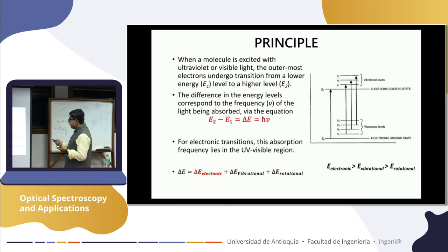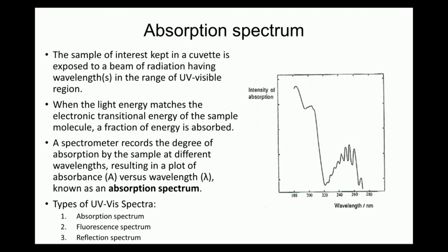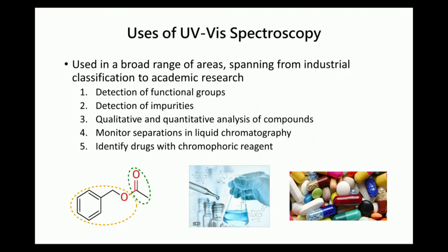That's how we measure the absorption of the material as a function of wavelength. A limitation in UV-Vis is that the light has to be high enough in energy to excite the electronic states. These are all electronic absorptions: you have to make the material go from the valence band to the conduction band, so your light energy must be enough. Then we could create a spectrum of wavelength versus intensity. All kinds of molecules, organic and inorganic, mostly drug design compounds, are studied through UV spectroscopy. Basically it's mapping: send one type of light, measure the intensity, and keep changing the light.